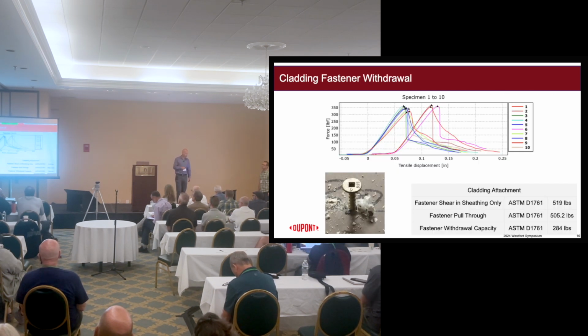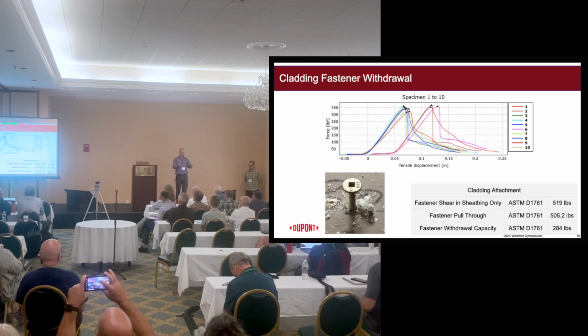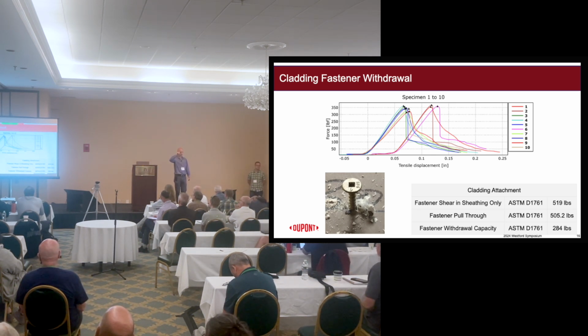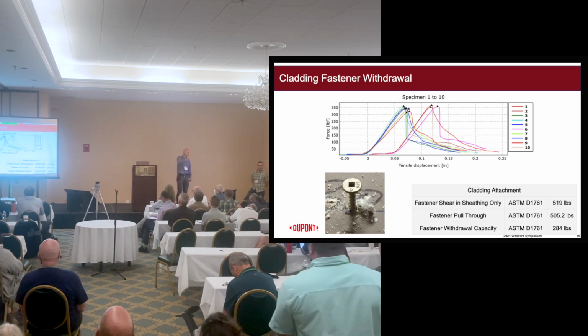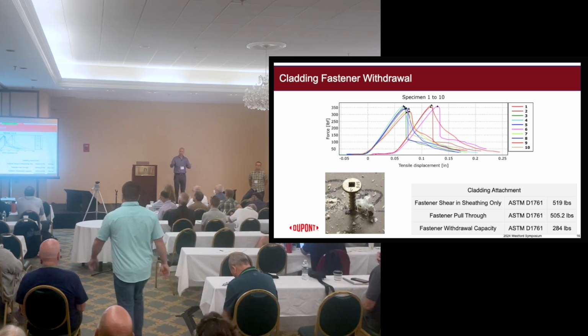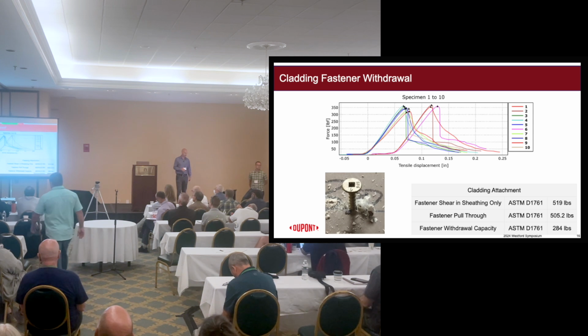So I've shown here, this is an example pull-out test. Just putting a fastener in and then just ripping the fastener out. The specification that DuPont uses is something like 280 pounds of force to remove a single fastener. But when we start talking about design criteria and actually putting on cladding, we're operating at below 100 pounds force. So look at that curve, think about how much force it takes to actually pull that out, and we're operating in the very bottom end of that stress strain curve. So very strong,